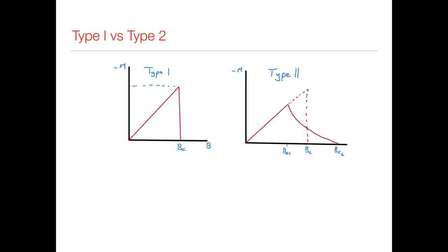Okay, so just to summarize, we've got our type 1 material in which interfaces cost energy, and so we only have our interface at the surface of the material. And there we get the perfect diamagnetism all the way up until the critical field. And then our type 2 material, we get perfect diamagnetism up to this first transition field here. I've called this BC1. And between these two regions, we get penetration of the field.